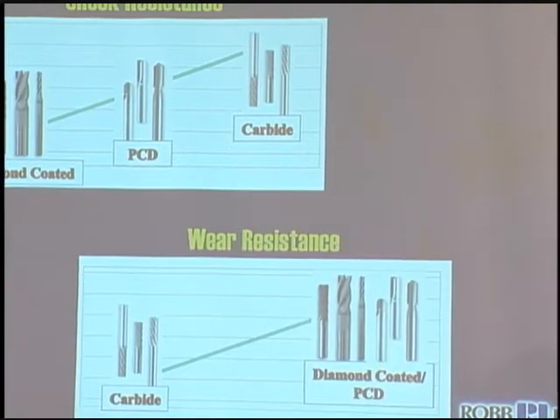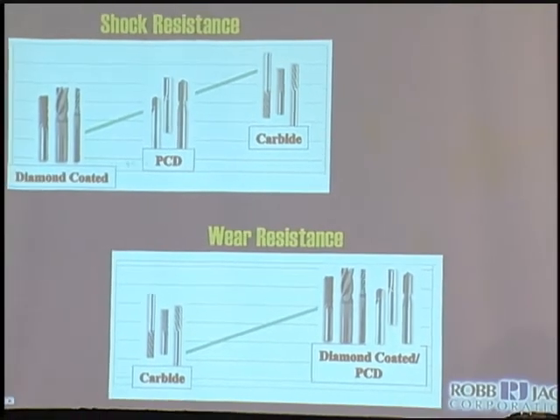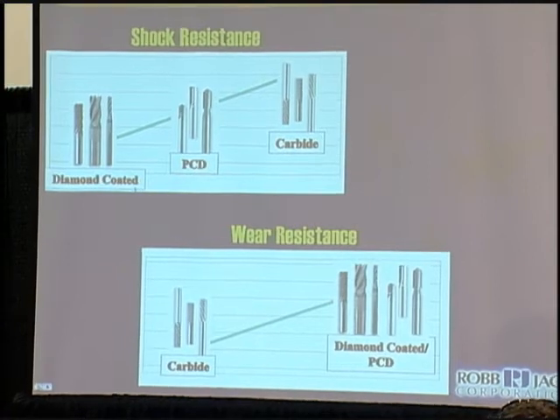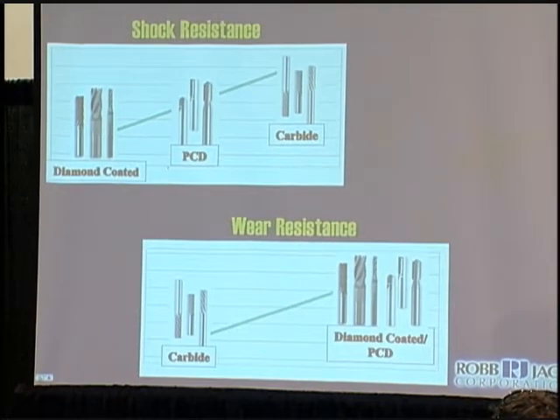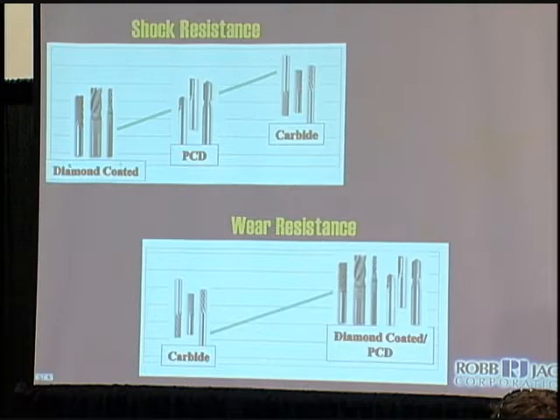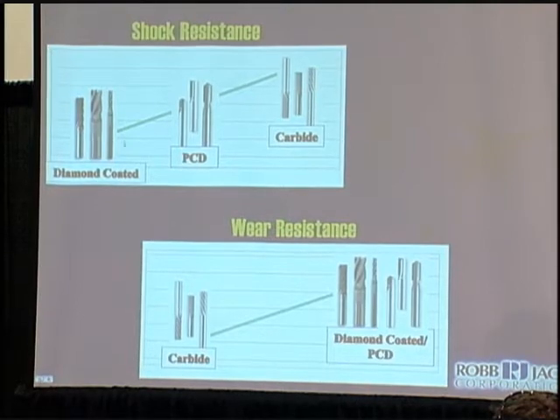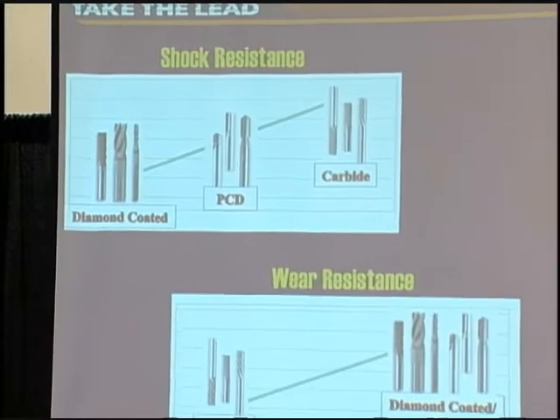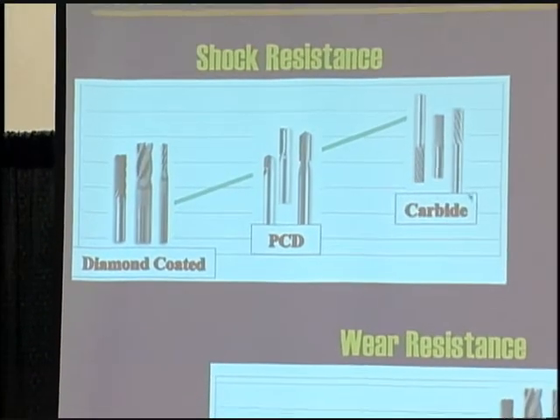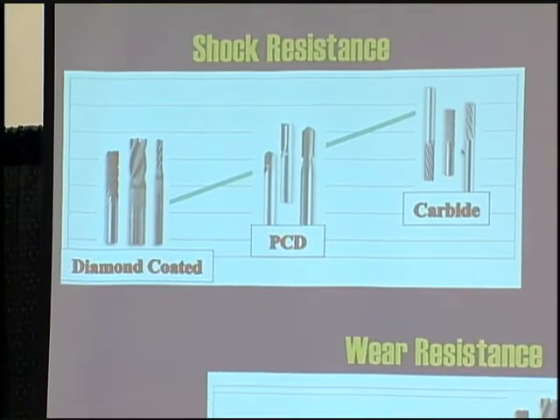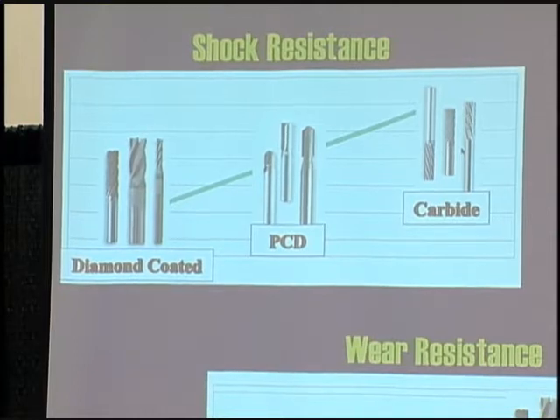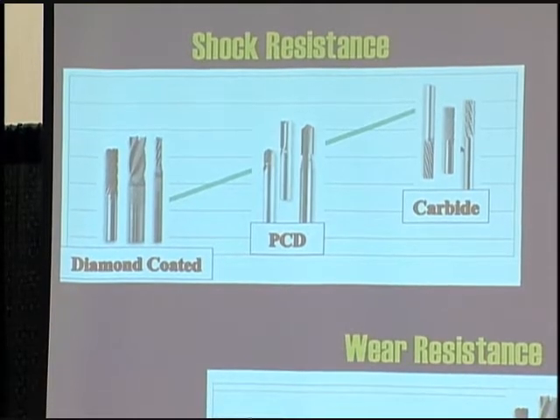So when you look at the three types of cutting tools, whether it be drills or routers, you have the diamond coating, the PCD, and the carbide. And when you look at the shock resistance, the diamond coated has the least shock resistance, PCD in the middle of the road, and carbide has the most shock resistance. So if you're having problems with chipping of your cutters because everything's vibrating really bad, you may want to stick more towards the carbide, because that'll give you the most shock resistance.